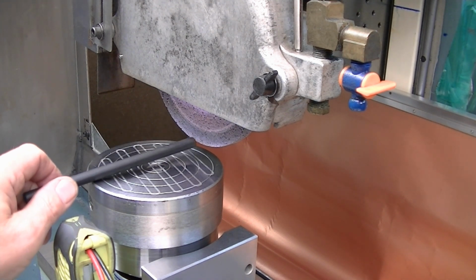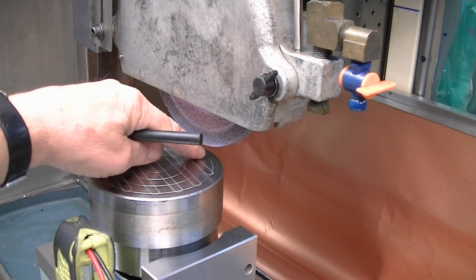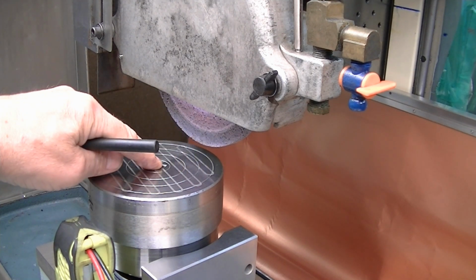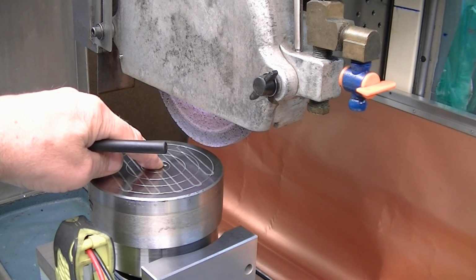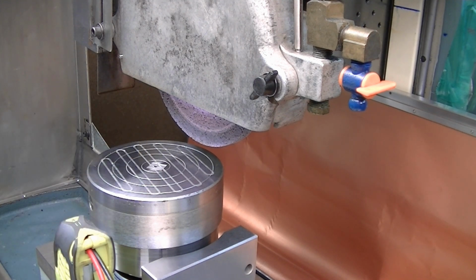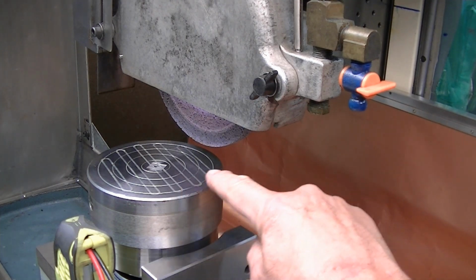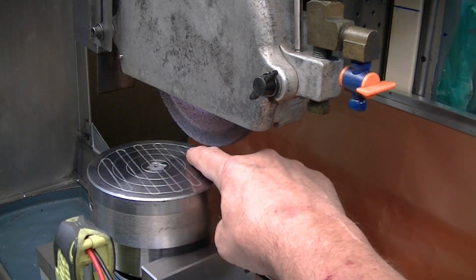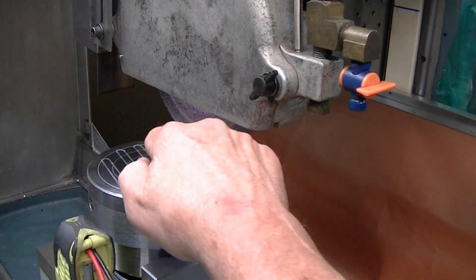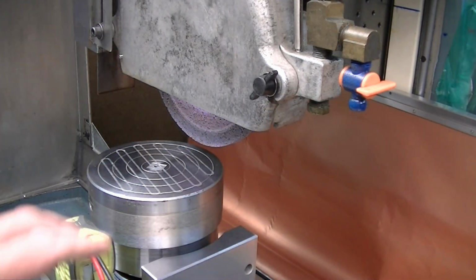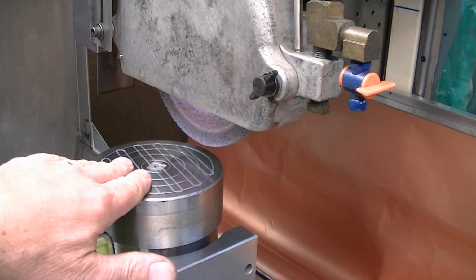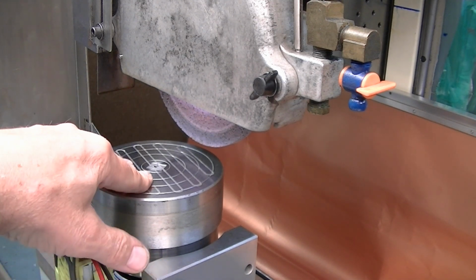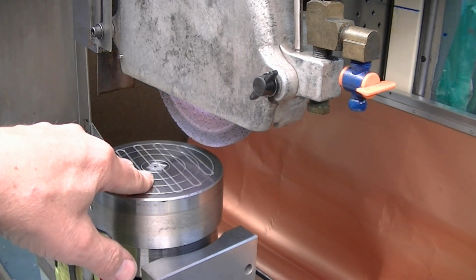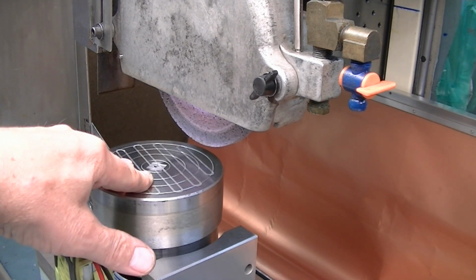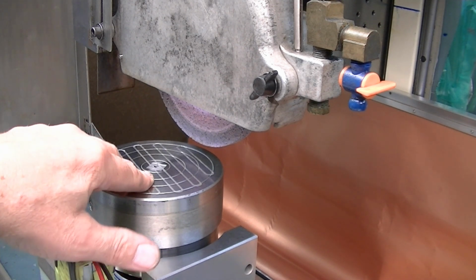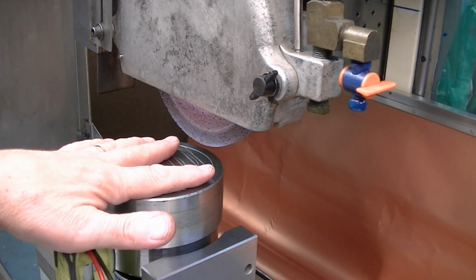Why can parts off of here be generally flatter than on the surface grinder? Well, in this, the only thing that controls the trueness of the surface ground along here is the trueness of one axis, the z-axis of the grinder moving in this direction, back and forth. So however straight that is, that's the only axis that's in motion other than this rotary axis. And this rotary axis typically is going to be a lot more accurate than the traverse can be on a grinder, because the traverses on a grinder can have roll and yaw and twist and things that will cause the surface to not be flat.